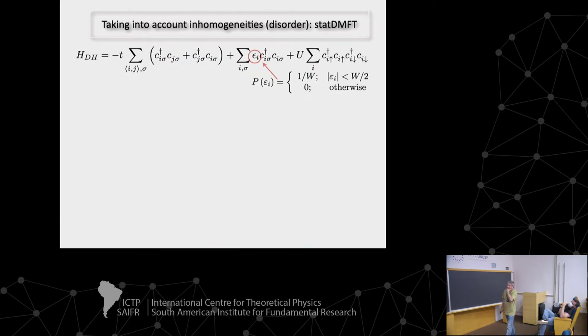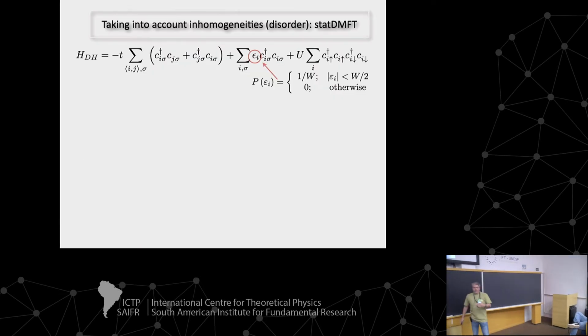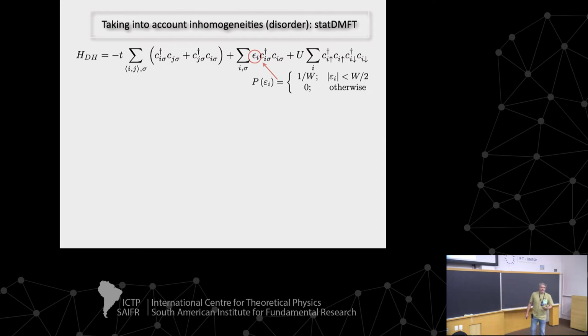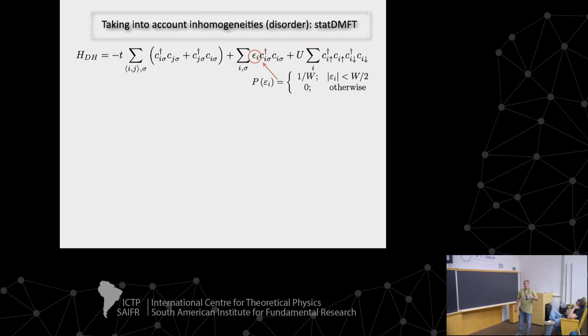Now, of course, to have inhomogeneities, you have to put disorder. Disorder will tip the system that's at the critical point or at the phase transition to one side or to the other, depending on the local value of the parameters. So the easiest way to do that is to assume a disordered Hubbard model where you put some random on-site energies distributed with some distribution. It doesn't matter too much which kind of distribution you use. What I'm going to talk about is for a uniform distribution of site energies.